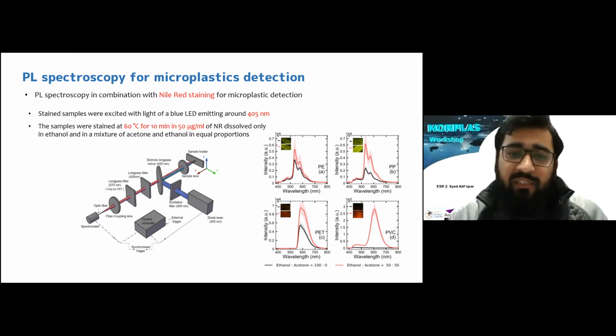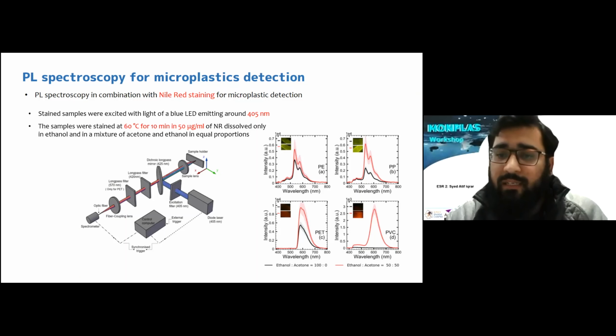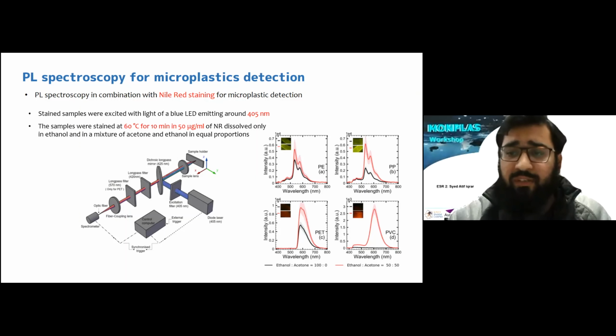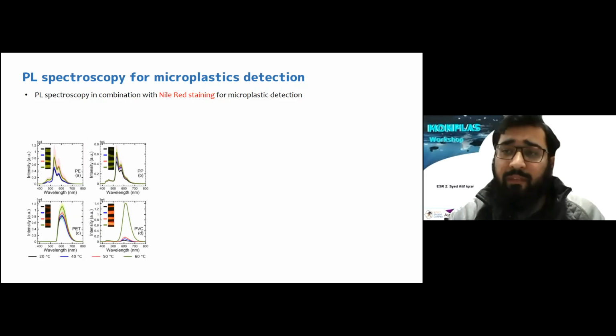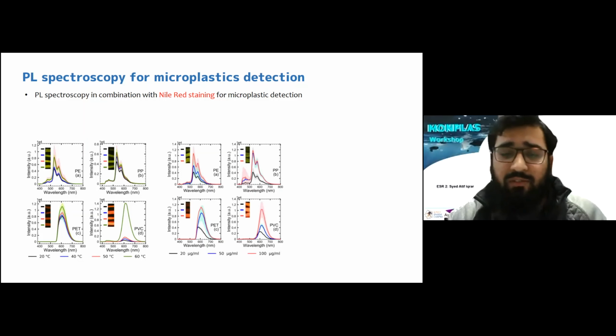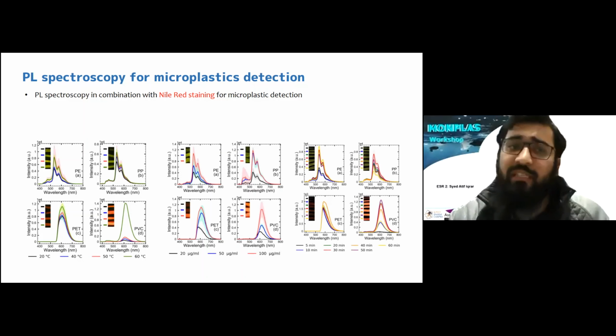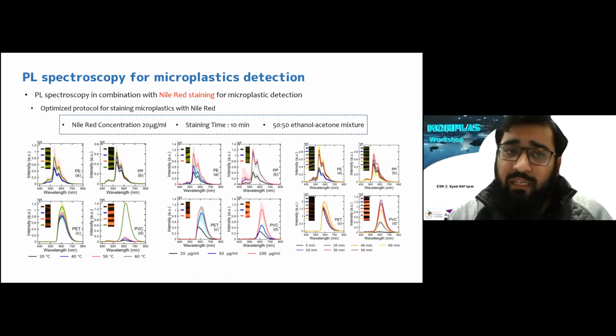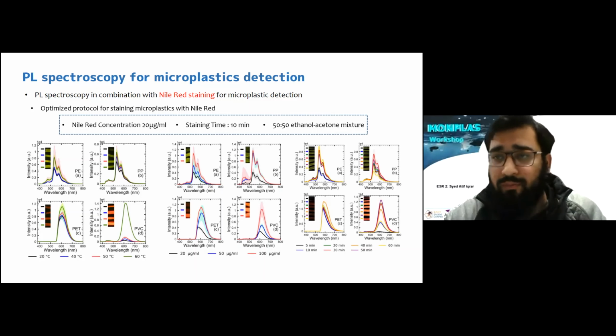So in the picture below, you can see the setup they used. It is quite similar to the previous one, and they used the solvents acetone and ethanol. In the first experiment, they used ethanol 100%, and in the second experiment, they used acetone and ethanol in a 50-50 ratio. And they got different spectra of 4 different plastic particles. They also performed the experiments at different temperatures, with different concentrations of Nile red and at different times. They finally concluded and optimized the protocol for Nile red staining of microplastics: a Nile red concentration of 20 microgram per milliliter, staining time of 10 minutes, and an ethanol acetone mixture of 50% is the best and optimized protocol for the detection of microplastics.